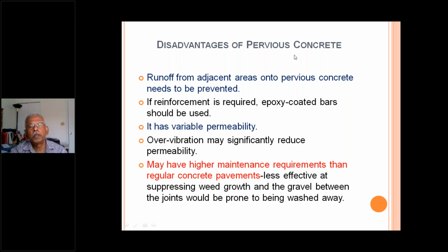Of course, there are some disadvantages of any product. Here, the runoff from adjacent areas into pervious concrete needs to be prevented. Usually, reinforcement is not provided, but if it is provided, epoxy coated bar should be used. It has variable permeability. That is, permeability may not be the same throughout the area. Over vibration may significantly reduce the permeability. It may have higher maintenance requirement than regular concrete pavements, is less effective at suppressing weed growth, and the gravel between the joints is prone to being washed away. So you usually provide a curb.